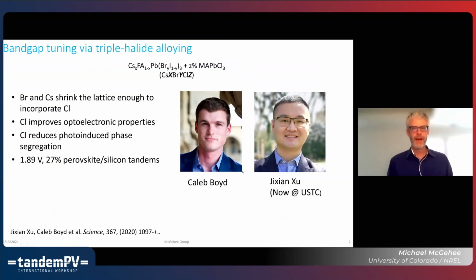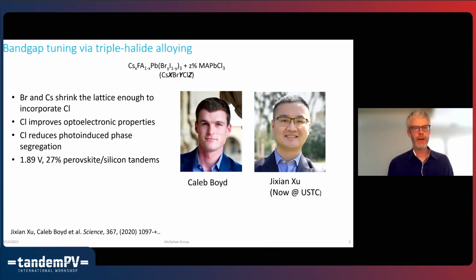Okay, so I'll just have one slide about the tandems that we described last year in Science. Try to hit some of the highlights from what Caleb Boyd and Jixian Xu did. We introduced a triple halide for the wide bandgap cell. We found that you can incorporate a substantial amount of chlorine if you have also used bromine and cesium to shrink the lattice. And then there's a lot of beneficial properties of having chlorine. It increases the carrier lifetime. I don't know if it necessarily directly prevents photo-induced phase segregation, but it allows you to get the target band gap with less bromine, and that certainly reduces photo-induced phase segregation. And so, using that, we were able to make a 27% efficient perovskite silicon tandem.